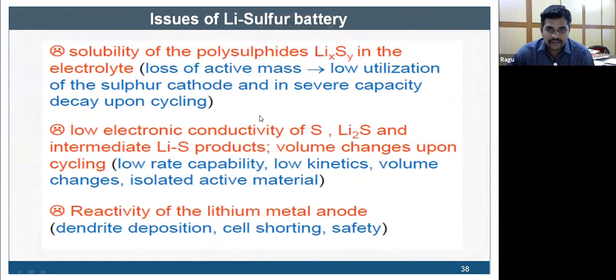Look at this lithium sulfur. Although you have seen that the energy density for lithium sulfur is much higher, yes, fine. But what is the issue? The issue with lithium sulfur is the solubility of polysulfide. When I say polysulfide, it's nothing but the active material. Once the active material is dissolved in the electrolyte, the activity of the battery is lost. Similarly, there is low electronic conductivity. As we have seen with lithium iron phosphate, poor electronic conductivity, you have seen in the table. Similarly, sulfur is also known for low electronic conductivity. So the energy density is much higher, but there is also a problem. That's why lithium sulfur and lithium air have enough challenges to address.